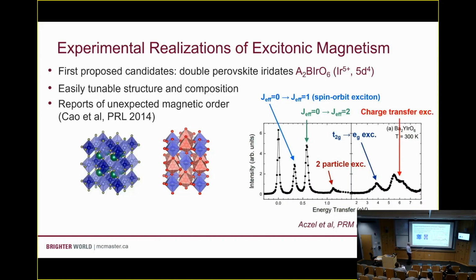We actually looked at some of these materials with RIXS, and you can use RIXS as a way of mapping out these orbital energy levels. You get a nice picture here of energy transfer, and you can see these peaks where we get dd transitions from one orbital to another. And we'll talk more about this in a minute, but the key point here is that the excitonic energy gap that we're trying to close in these excitonic magnets is this gap here, from E equals 0, so where our ground state is, to this peak here, which corresponds to the first excited state, the spin-orbit exciton, that J effective 1 state.